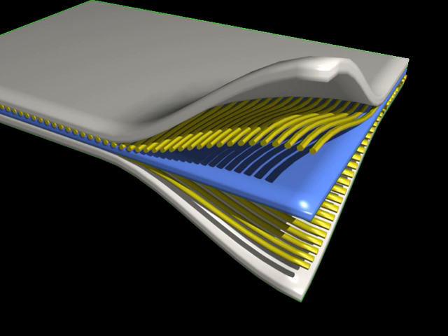Finally, for large values of theta near pi/2, transverse matrix failure is the most likely to occur, since the fibers no longer carry the majority of the load. Still, the tensile strength will be greater than for the purely perpendicular orientation, since the force perpendicular to the fibers will decrease by a factor of 1/sin theta, and the area decreases by a factor of 1/sin theta, producing a composite tensile strength of sigma_perp / sin^2 theta, where sigma_perp is the tensile strength of the composite with fibers aligned perpendicular to the applied force.